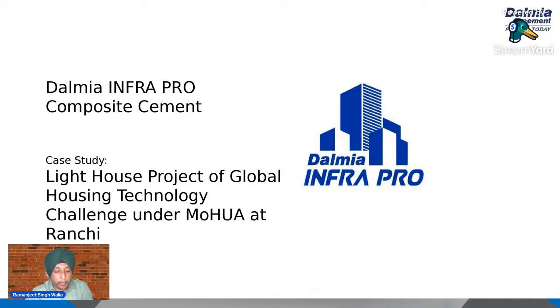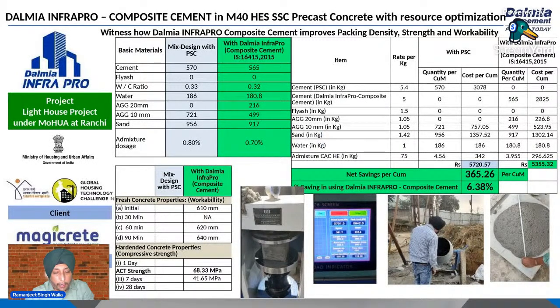This is a lighthouse project in Ranchi where we have done trials with composite cement for early strength. Their requirement was 25 MPa in 24 hours. Recently we have done these trials and the result was 68.3 MPa in 565 kg cement. Earlier they were trying with PSC and OPC also, and were not getting results because the workability requirement was a minimum 550 flow in 90 minutes. Using this Dalmia Infra Pro composite cement, we were able to achieve early strength along with the workability requirements.